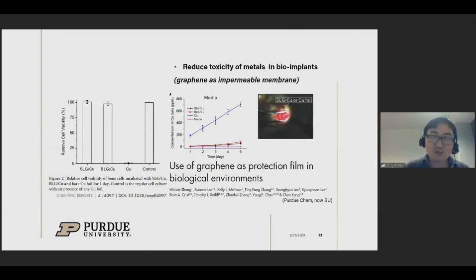And one situation where this is actually important is in the area of bioimplants. This is nice work with former Purdue colleague Chen Yang, who has now moved to Boston. They put our graphene around copper. In this experiment, the aim is to suppress ions from copper that can get into, for example, blood if the metal-based bioimplant is inserted into tissue, and that causes problems. By wrapping the metal with graphene, it blocks these ions from getting into the blood, which suppresses the toxicity of these metal-based bioimplants. That's an important potential use of graphene in bioengineering.